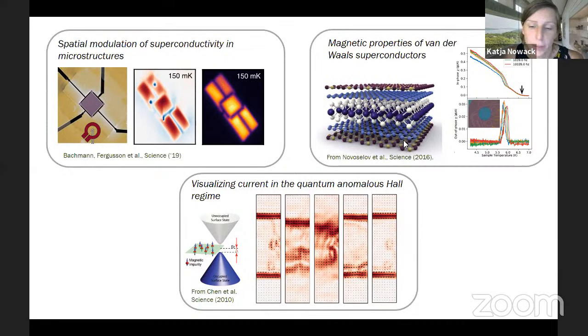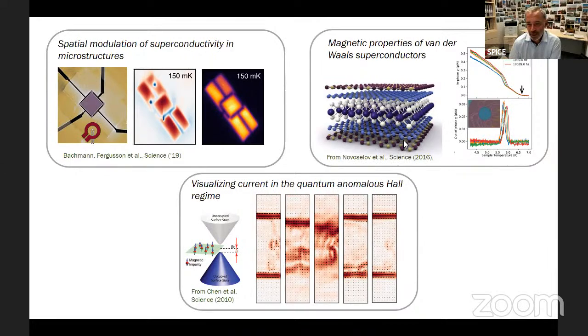And so we're really limited to measuring at the value of the magnetization that remains in the sample as we return to zero field. So we really don't have that as a tuning knob. So I can't answer that. There's no answer. We had to measure it.